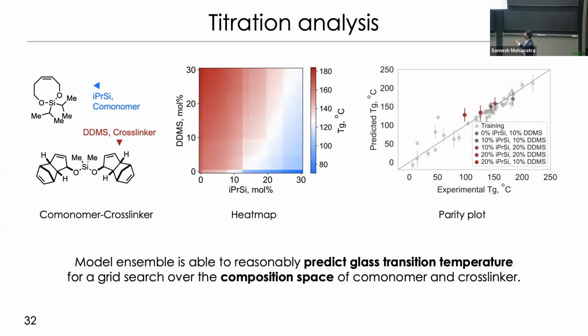And if you increase the co-monomer to 30% and no cross-linker, it should get to the lowest TG in this case. So the model really understood what this entire co-monomer cross-linker composition landscape's glass transition temperature was, which was very satisfying. And taking data points from this landscape, we went back to the lab, and Yasmin validated them in these experiments, and it turned out that yes, the model was able to actually predict them reasonably well.